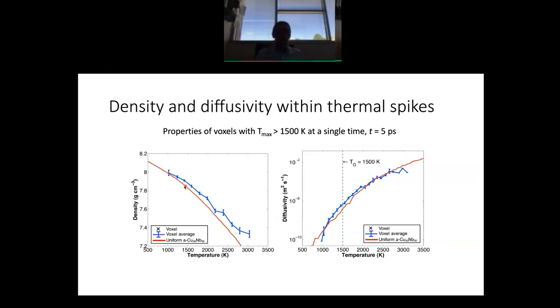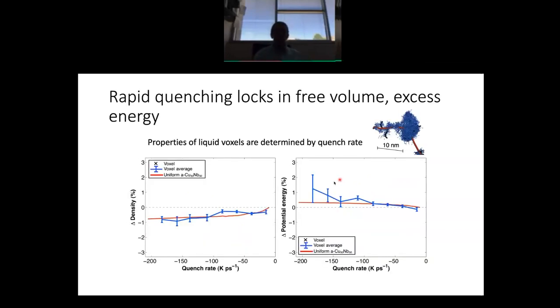Here is a plot of the density versus the temperature in the thermal spike. As the temperature is high, the density is low. When the temperature drops, the density becomes higher. When the temperature is high, the diffusivity is high. When the temperature drops, the diffusivity is low. And I'm just indicating here where the glass transition temperature is for this particular material. Now, as I showed you a few slides ago, when you very rapidly quench a liquid through the glass transition temperature, you're left with a little bit of excess free volume. That's something that we could quantify out of these simulations.